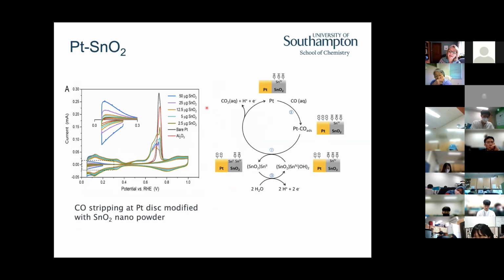right? And what the data showed then was that this OH sitting on the tin near the platinum is really mobile. So in platinum tin electrocatalysts, one of the reasons companies have not been so keen on pursuing this is they were worried if you go to too high a potential, and that's where you go to when your fuel cell's at rest, right? When the oxygen is allowed to permeate through, then you reach these higher potentials. And people worried that as the tin dealloys, that you're losing all your activity.